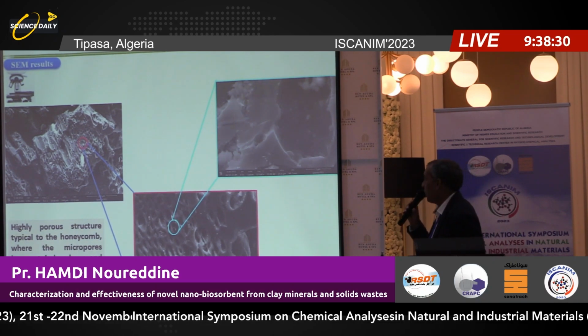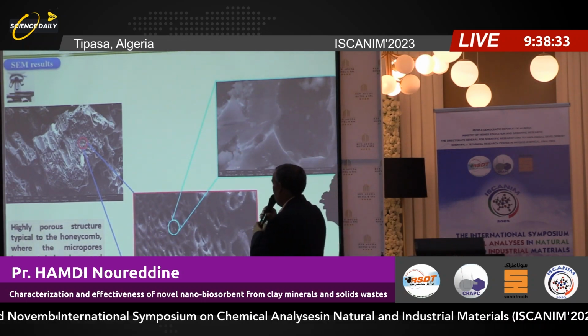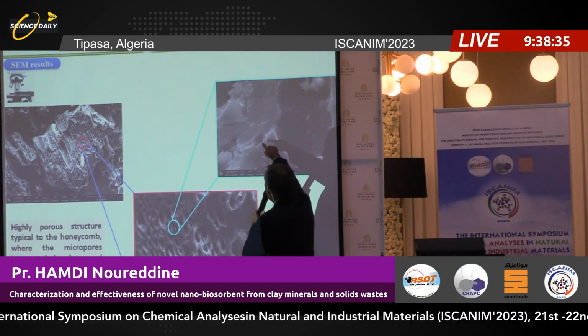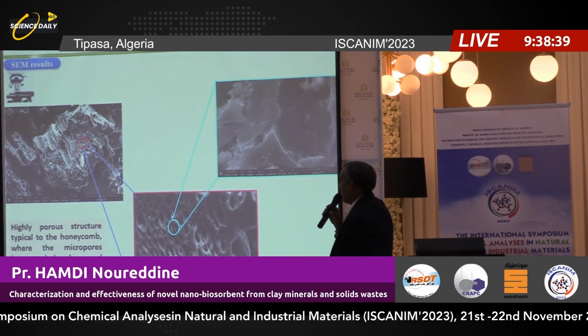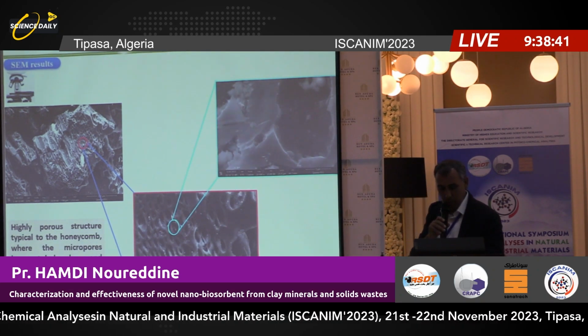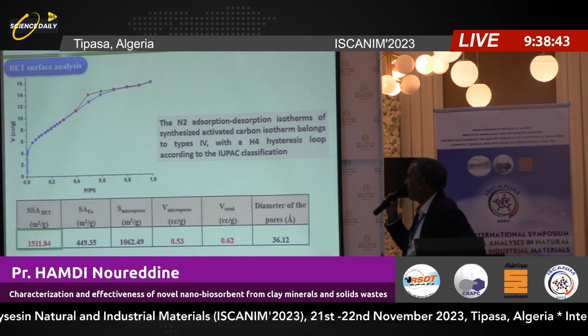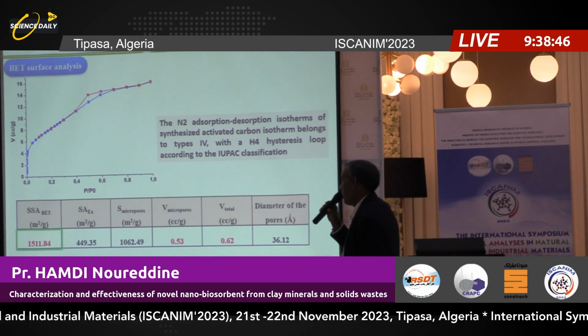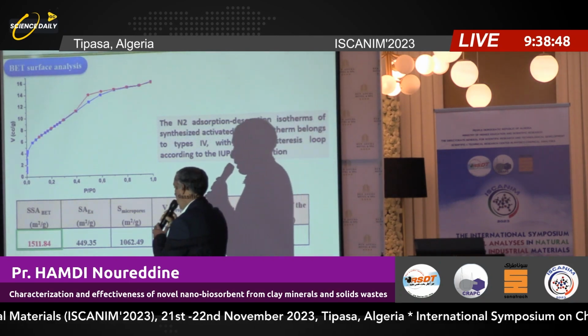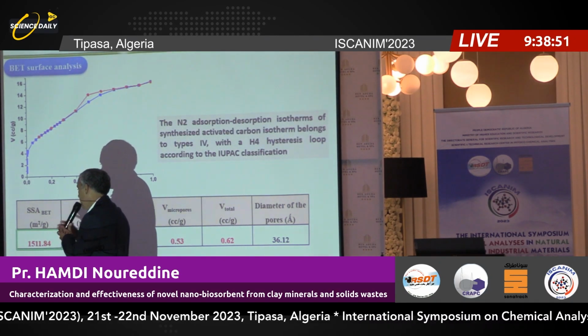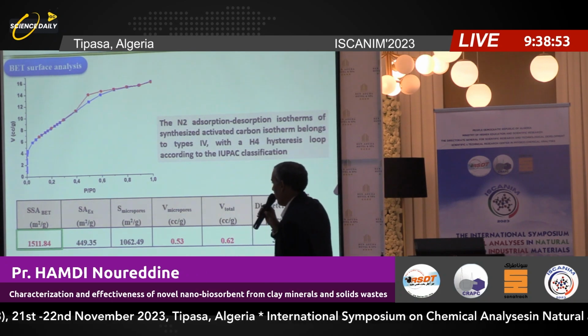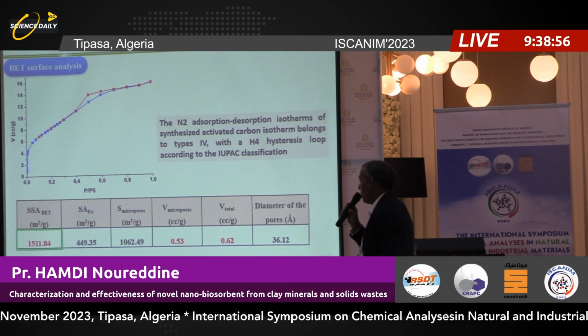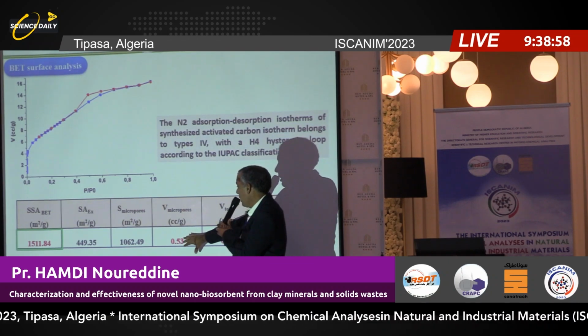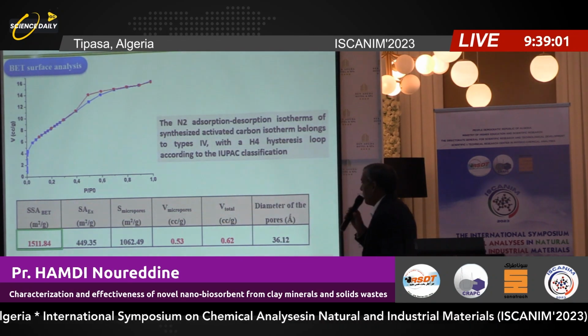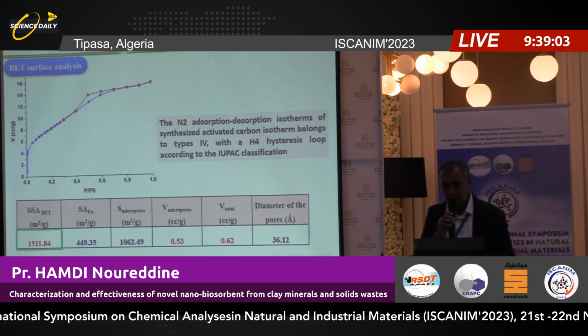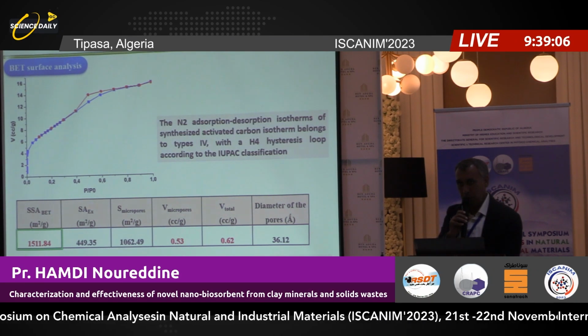gives an idea about the porosity, the canal porosity, and in the canal you can find very nano pores. The specific surface area of this activated carbon is very high compared to the commercial activated carbon, about 1,511 square meters per gram, and the majority of the porosity is micropores, a very, very developed surface area in this new material.